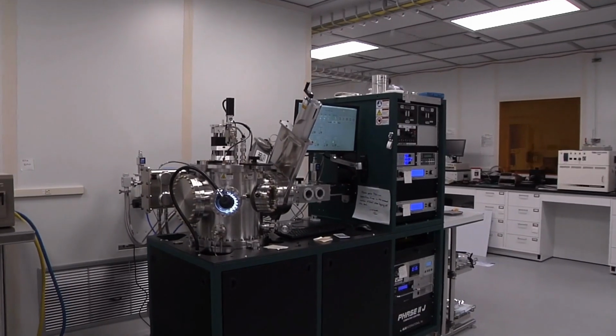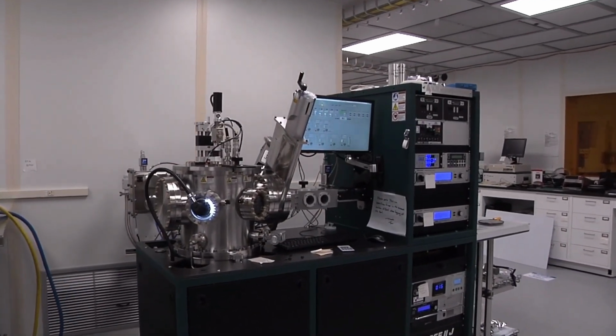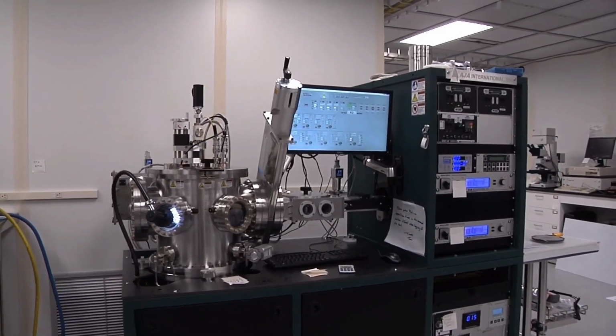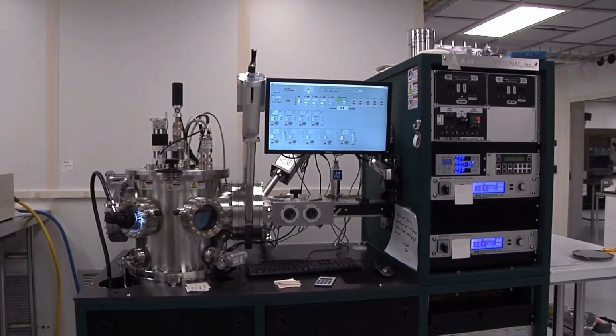The difficulty with this sputter deposition process is that it's very difficult to make a layer that's thick enough for their calibration standards. The thicker you make it, these films tend to have very high mechanical stresses, and so they tend to crack and peel off and break. And so this was not a common way for anybody to make thick chrome layers. So I had a very good PhD student, Nate Rogers, who worked on this. We used an AJA deposition system that's at the Cornell nanofabrication facility. You're looking at a picture of that one here.